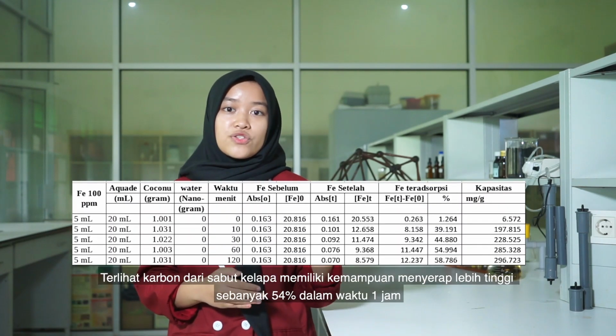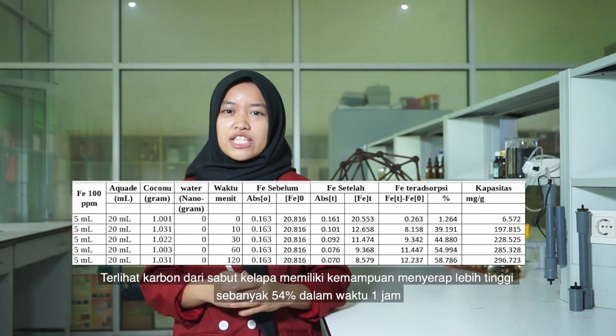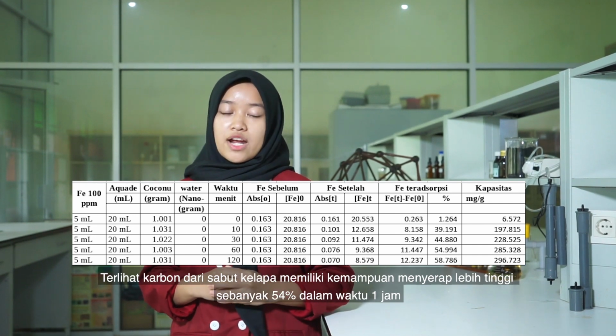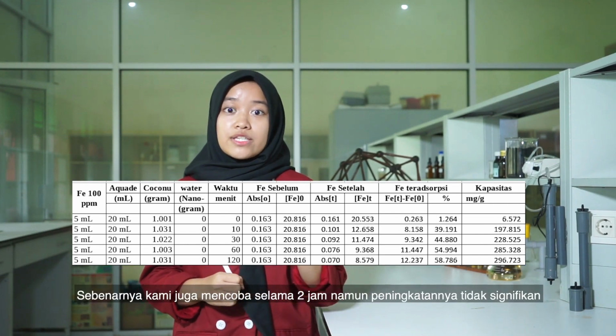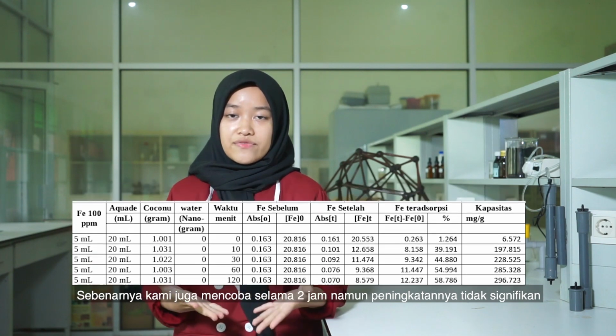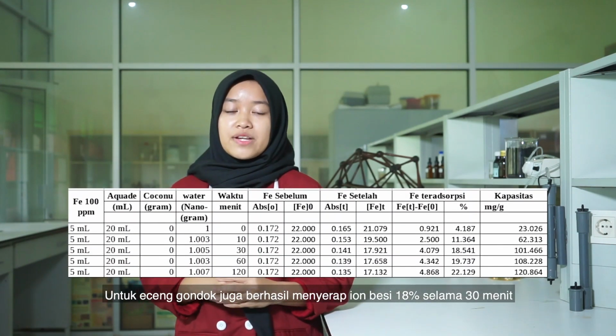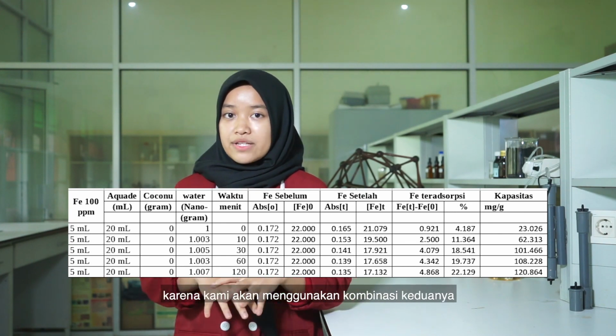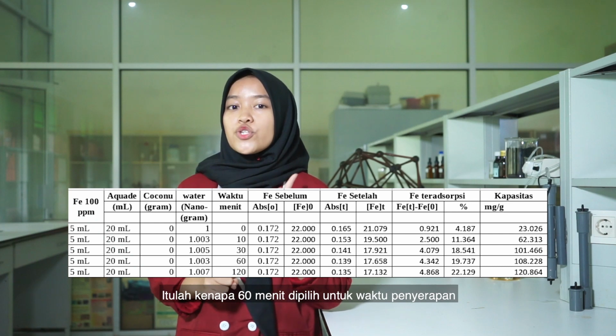To know the effectivity of the carbon, we started by determining the maximum absorption time. It can be seen that coconut fiber has the higher ability to absorb iron ions, as much as 54% within 1 hour. Actually, we also tried for 2 hours, but the increase is not significant. While the water hyacinth can absorb 18% within 30 minutes. But because we will combine these two components, 60 minutes was chosen for maximum absorption time.